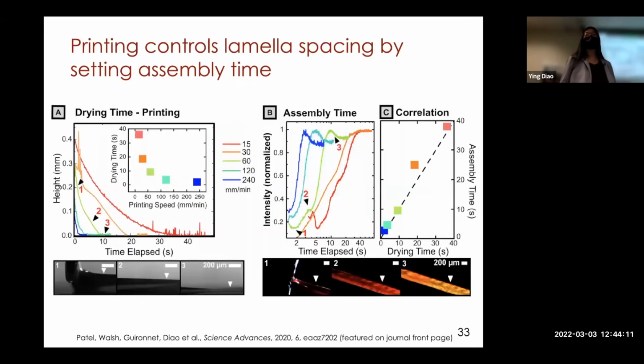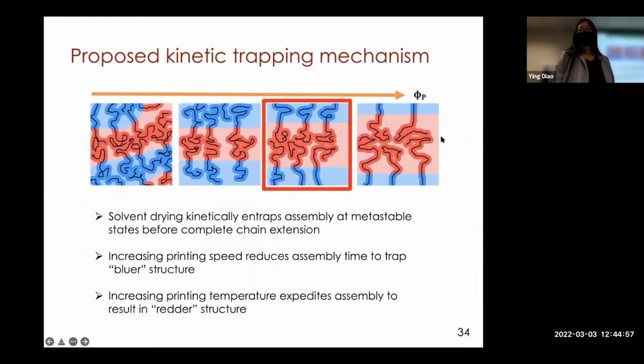And then the question is how the printing controls the spacing. It actually does so by setting the assembly time, we figured out. We determined that the drying time scale varies as a function of printing speed. Basically, the faster we print, the faster the drying time and the bluer we get. And then we also separately mapped out the assembly time. And most importantly, we figured out that the drying time actually sets the assembly time. Basically, if we dry faster and faster, we arrest the assembly before it reaches equilibrium, and therefore arrest the bluer state. So here shows the mechanism that we determined.